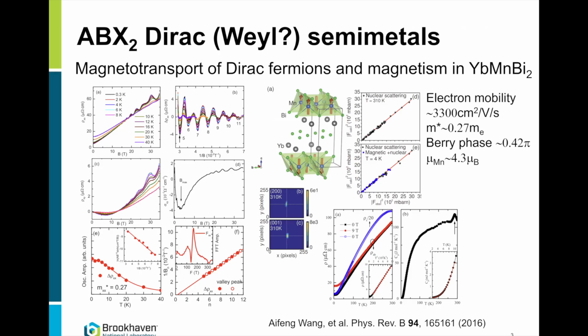And still, at the same time, the Dirac layers do not scatter and show very high mobility, several thousand centimeters squared per volt-second. So these are excellent systems to investigate whether one can manipulate Dirac electrons. Dirac systems are considered to be very promising for all sorts of electronic applications, starting with graphene, because low electronic densities are amenable to tuning. And here the idea is to see whether they are amenable to tuning with magnetic moments of the